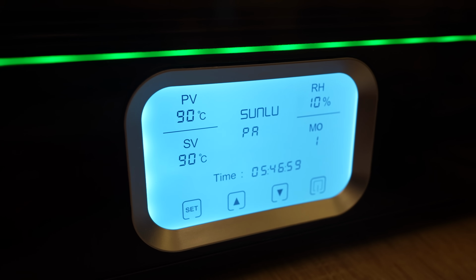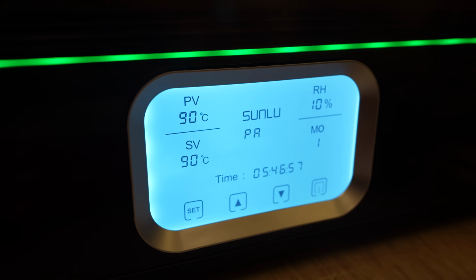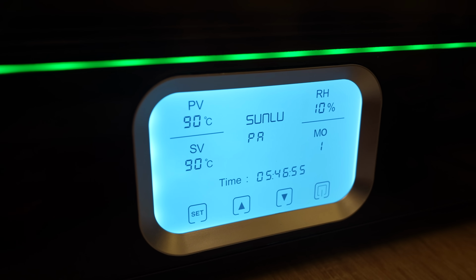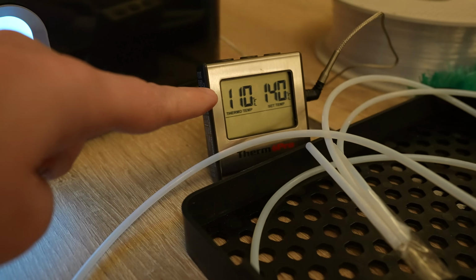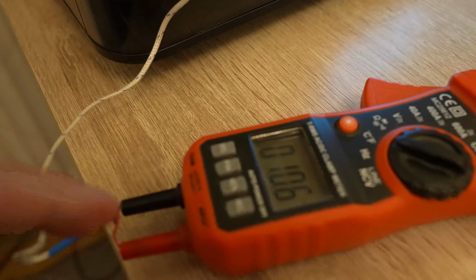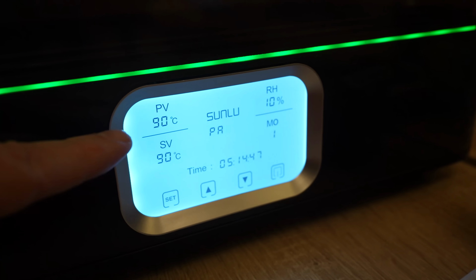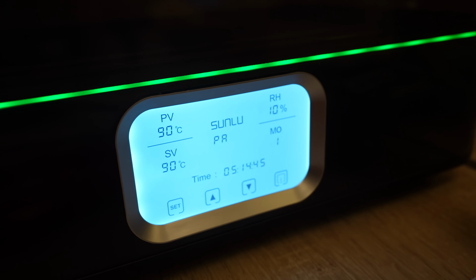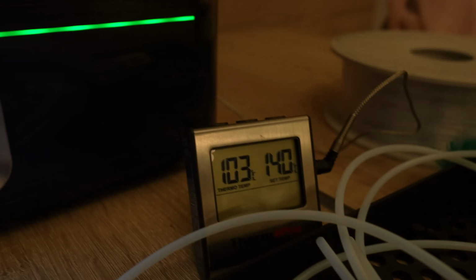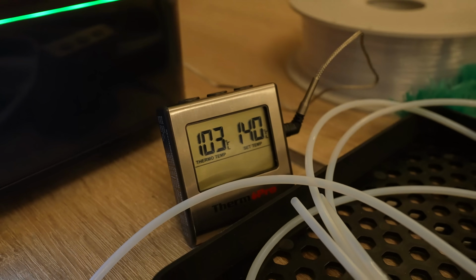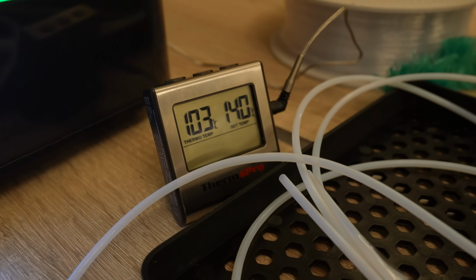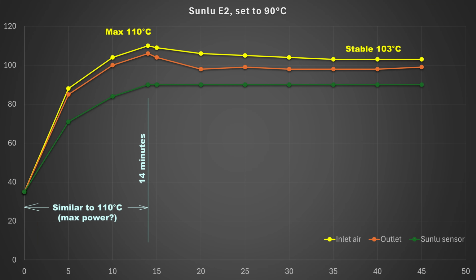It reached 90 degrees Celsius according to its own sensor in only 14 minutes. But the other two temperatures, 110, 106. According to the Sunlu sensor, the temperature stabilized after 14 minutes, but I can see that the circulating air stabilized only after half an hour. Now this graph is a little bit different.